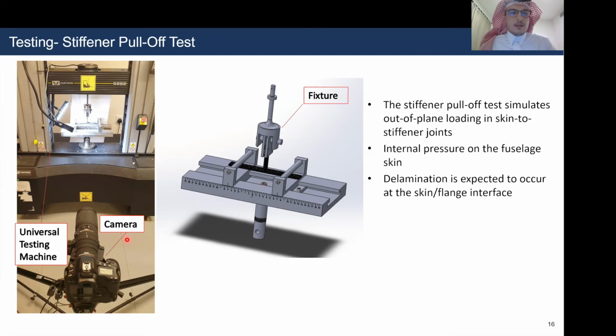And the fixture was actually designed previously by me, because I'm the first one in the lab or in our center to work on T-joint structures. So we had to design a specific fixture using SolidWorks, and then the pull-off test actually simulated real-life conditions of internal pressure on the fuselage skin, for example. The delamination was expected to occur at the interface between the skin and the flange, because this is the area where the strength is the lowest.